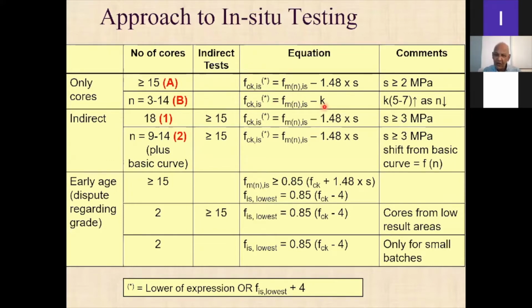minus K. So K, of course, is a function of the number of cores that you have taken, between 3 and 14, right? So if the number of cores is less, the K value will increase. Therefore, your estimated in situ strength will go down, right? Similarly, in situ strength is also something like that, right? And you can go through this procedure, and I will go through that little by little, right? This one also I will go through in all these slides, but once again, I would like to highlight the objective here for older concrete is to estimate the in situ strength.